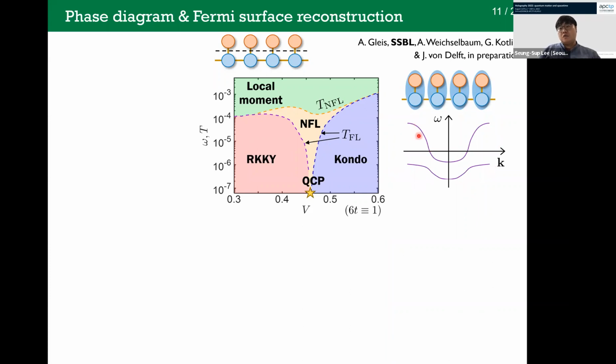We can understand these two bands in terms of the hybridization of the dispersive conduction band and the flat f band. Due to the hybridization between this coupling, we have this hybridization gap, but of course it is many-body physics. So the position and the size of the hybridization gap is strongly renormalized to a value on the scale of the Fermi-liquid scale, which is much smaller than the bare energy scale.